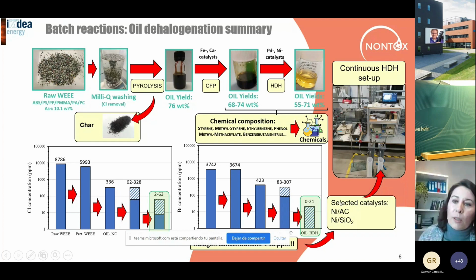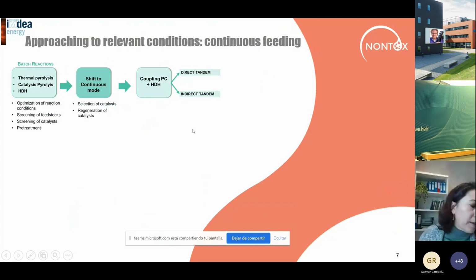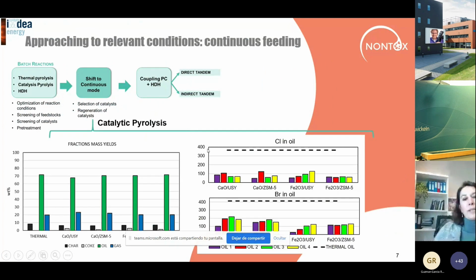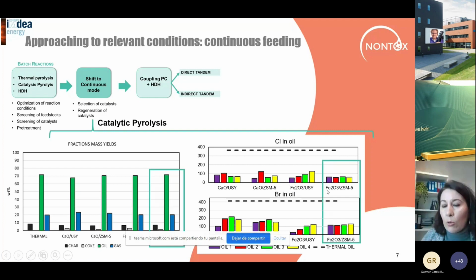We selected the most promising catalyst, and then we moved to the next step, in which we evaluated the catalysts and the feedstocks in a continuous mode in order to approach more relevant conditions, conditions closer to a real plant. And here you can see the results regarding the catalytic pyrolysis step, where we were evaluating different catalysts, two based on calcium oxide and the other two with iron oxides. In these cases, we found that using iron oxide supported onto a zeolite, we were able to reach quite stable activities, at least during these 4 hours of the reaction, and with quite low halogen concentrations in the oil, with very high quality. And the oil yield was hardly affected. It was not penalized.